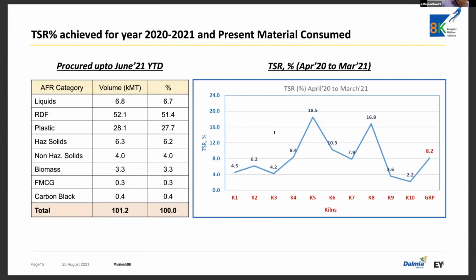The thermal substitution rate achieved for the year 2021, as I mentioned, was around 8.2%. For some of the kilns, it has been as high as 18.5% and 16.8%, where we have state-of-the-art facilities available and where RDF is available in substantial quantities, in plants located near big cities. In other locations, the quantities are low, in the range of 4 to 6% or 4 to 10%.